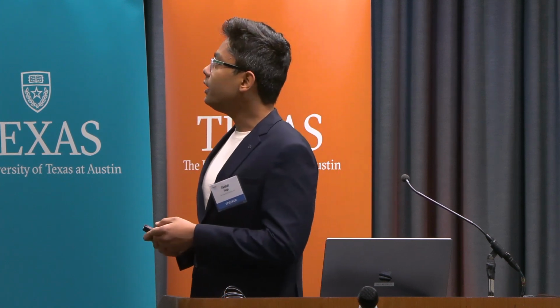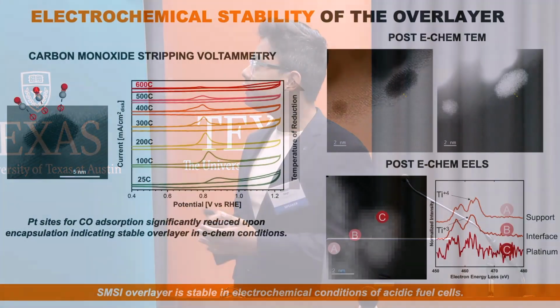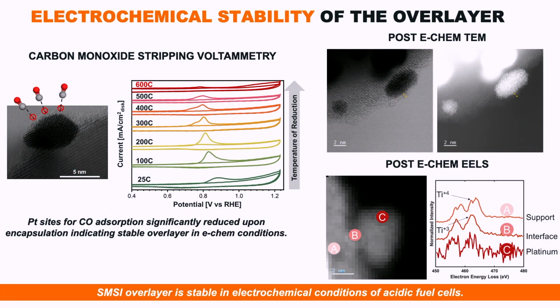So in order to test the electrochemical stability of the SMSI overlayer, we performed 3 experiments. Firstly, we looked at carbon monoxide stripping voltammetry, which is a technique that is used to quantify the number of accessible platinum sites to an adsorbate, which is carbon monoxide in our case. And what we saw was for the encapsulated version, which is the red curve at the top, the CO stripping peak area reduced significantly compared to the other catalysts, suggesting that the overlayer is still stable under the applied potential and pH.